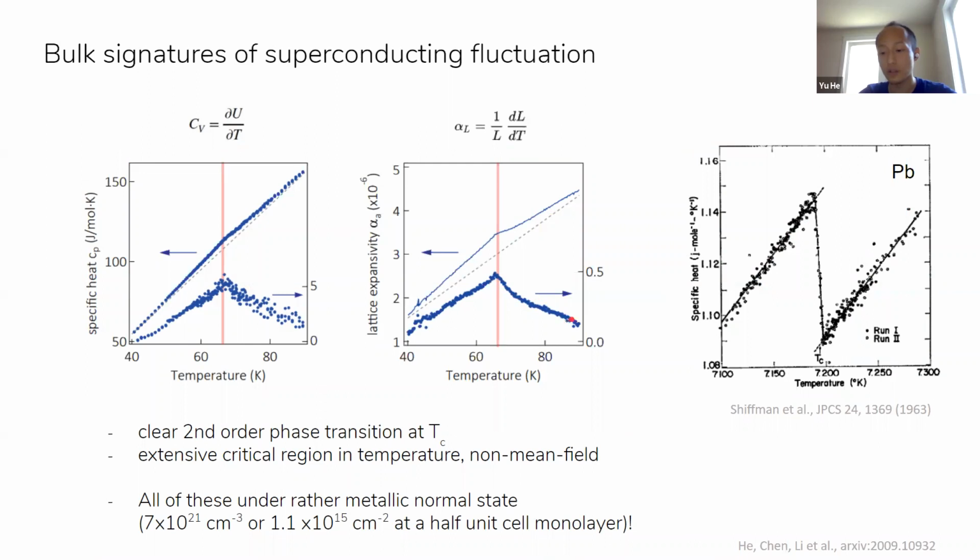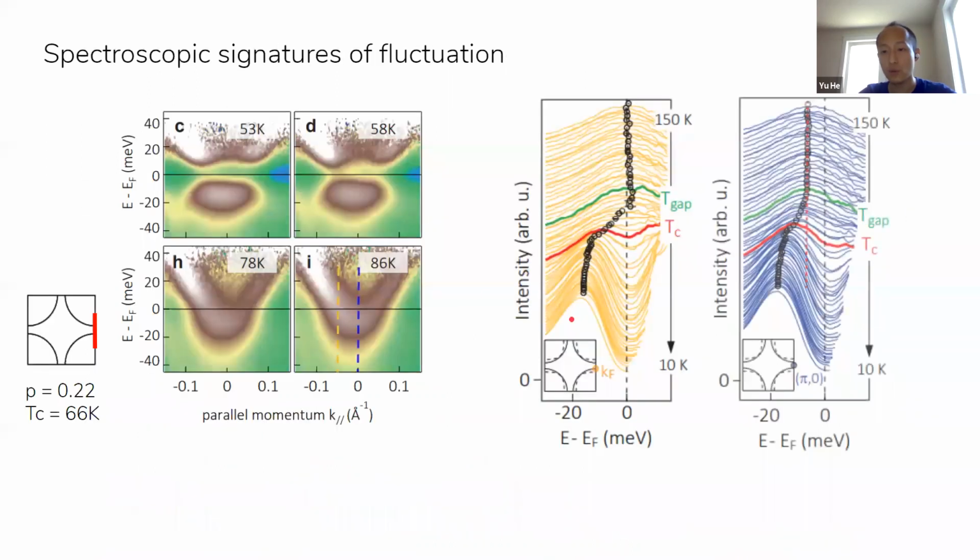Chimiao, to answer your question, in the presence of fluctuating superconductivity there will be diamagnetism, but the diamagnetism will not be directly proportional to the gap. It will be proportional to the superfluid density. Because in order to form the diamagnetic currents, you have to actually have global phase coherence to some extent. That's why above TC, even though there can be preformed Cooper pairs, the diamagnetic response is disproportionately weaker than what you would get in the bulk superconducting state.